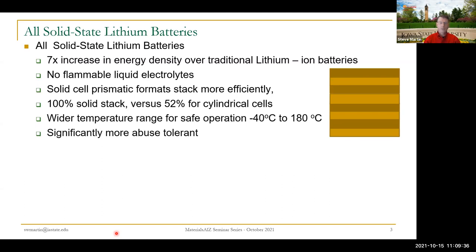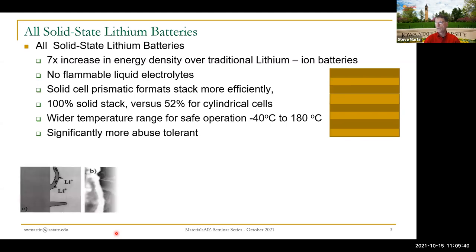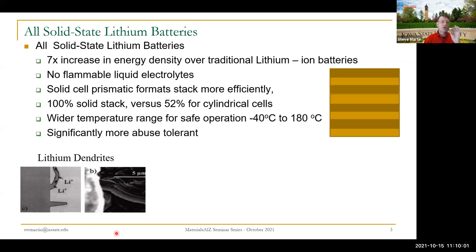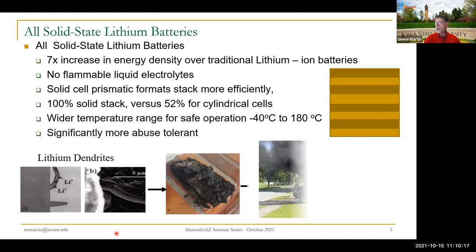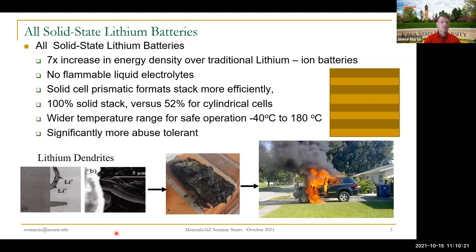Again, because they're based on solids, they're abuse tolerant, more abuse tolerant than liquid cells. One of the big advantages of solids is this ability, it's being developed, that these glasses and solid electrolytes can limit lithium dendrites. It's one of the main reasons for fires and explosions. These very tiny micron-sized filaments of lithium occur on high discharge and high charge rates. You know, we see in these skateboards and so forth, these filaments penetrate across the membrane, this plastic membrane. It's only 30 or 40 microns, and so they don't have to grow very long. They short out the cell, it catches fire, and then, of course, as you've seen here in many different pictures of this, it's a real catastrophic problem. So these solids not only are offering higher energy densities, but a safer operation as well.